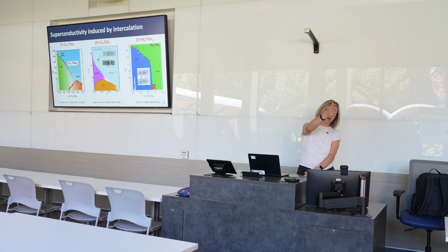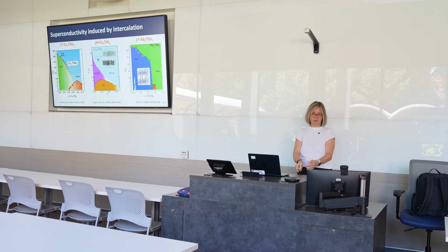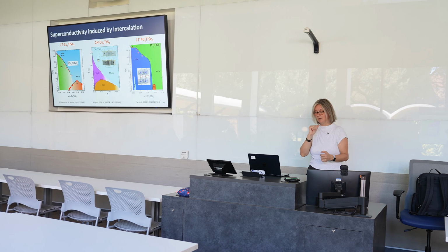And the dotted line and the dotted symbol there is because I still have a hint of it in some measurements, but it's not very clear. And it's because the phase boundary now becomes very vertical. So when you have a phase boundary that comes like this and you're trying to measure along that direction, you usually don't see much of a change in your thermodynamic or transport properties.